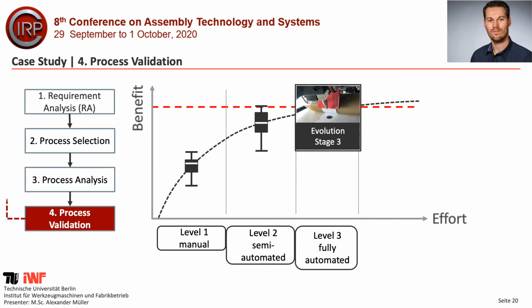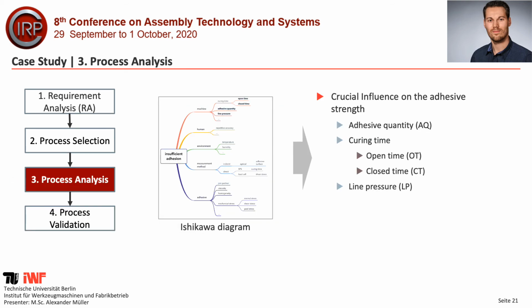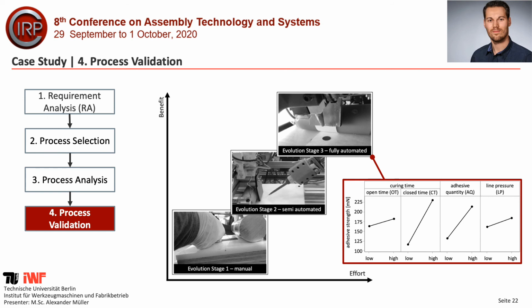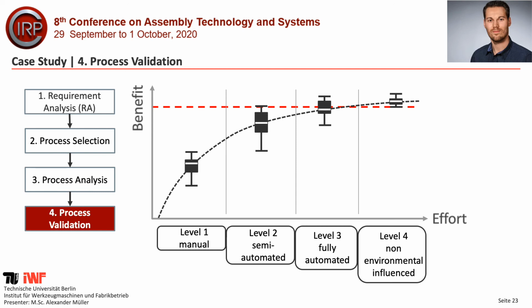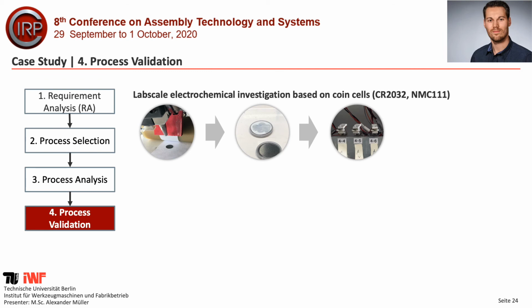So at this level we know which parameters have the biggest impact on the adhesive strength, and afterwards we do a DOE with these parameter setups. We see that the cure time, as an example, has the biggest influence, and so you can design your machine with these results. And so we don't have to go for level 4 because our accuracy level is high, but we have to build some coin cells because we have to check the chemical performance of the cells.